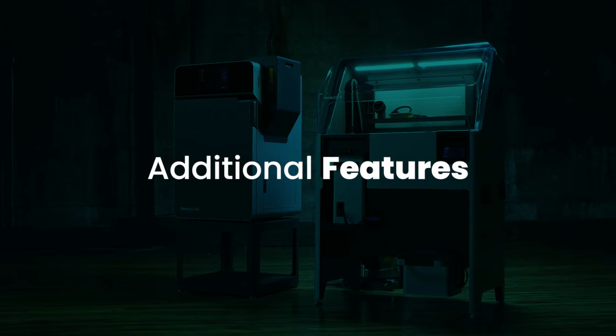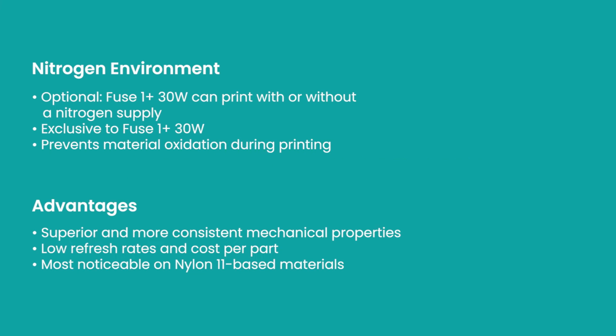The other new feature of the Fuse 1+ 30W is the nitrogen supply. You can run your printers in an inert gas environment. This is an optional feature that you can choose to use. It does have some advantages. For example, when the printers are running, they are raised to pretty high temperatures, above 150 degrees Celsius, depending on the material and maybe even higher. When these materials are exposed to such high temperatures, the materials will degrade, especially when there's oxygen available. And therefore, by using an inert gas environment, you can actually save the material from being degraded too much.